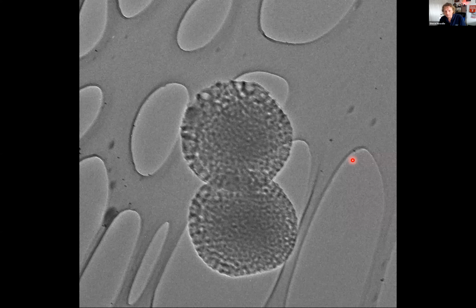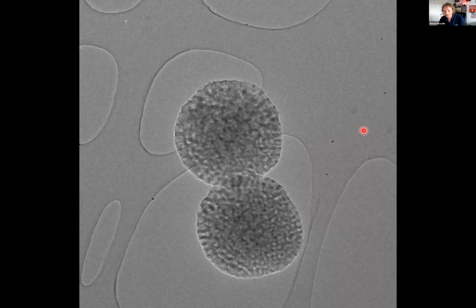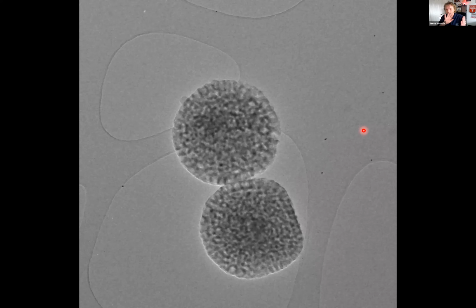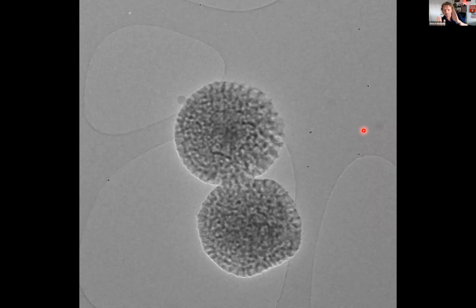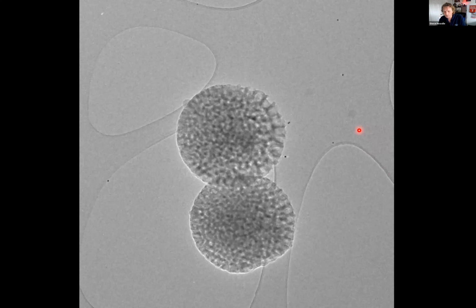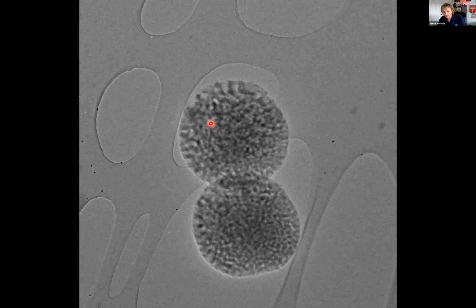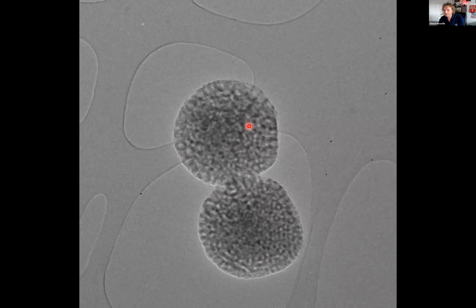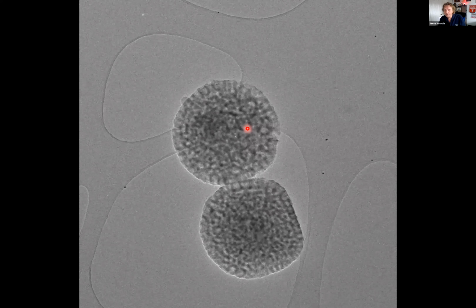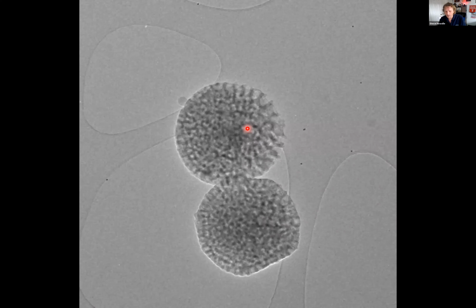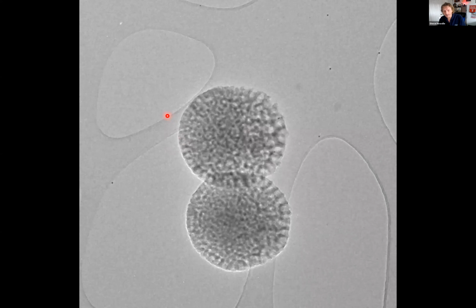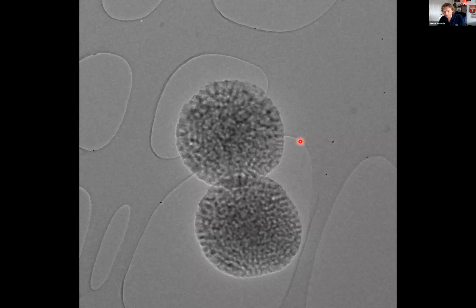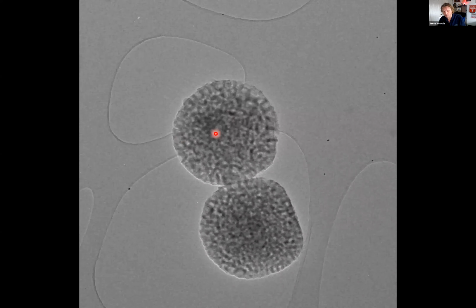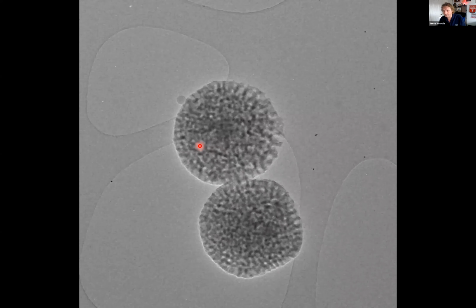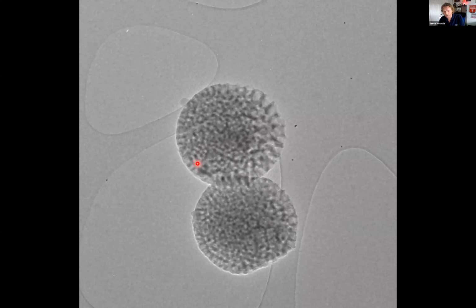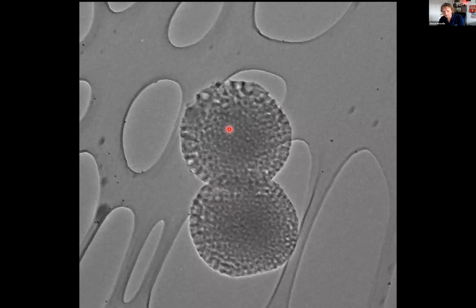Here are these particles inside the electron microscope, and you can see they've used the electron microscope to pan around the structure and to prove that these are definitely porous all the way through. So it's not just on the surface, and you can image this as you rotate these particles around. I'm still amazed by electron microscopy and the ability to manipulate these things that are just a couple of microns in size and move them around. Here you can see the very nice structural porosity that's in there.